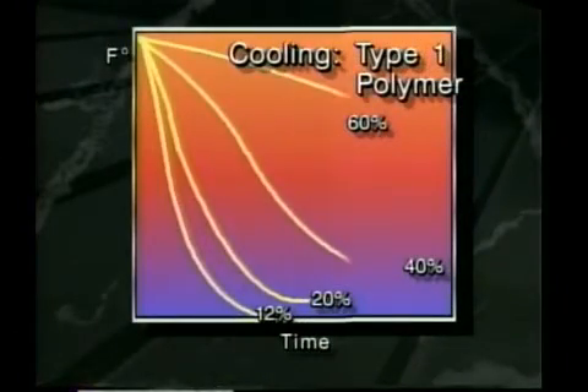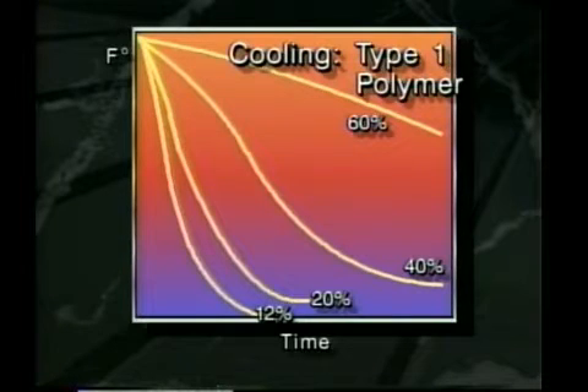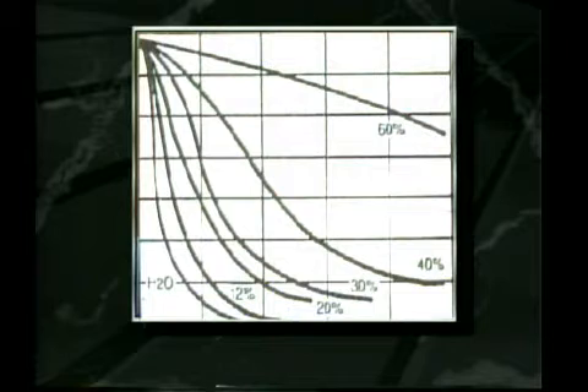The variation of the cooling characteristics is best illustrated by the review of the cooling curves for materials of different thicknesses. This illustration shows a series of curves for 1/2 inch 7075 aluminum alloy plates at different concentrations of a Type 1 polymer. It can be seen that the quenching characteristics vary significantly by simply changing the concentration of the polymer. Coupled with alloy quench sensitivity data, the heat treater can use this data to select a concentration that will provide him the proper quenching speed to achieve required properties in a specified part. When polymer quenching parts to military requirements, the concentrations of the polymers used are outlined in SAE specification AMS 2770, heat treatment of aluminum alloy parts. The requirements of selected alloys and forms are shown here.